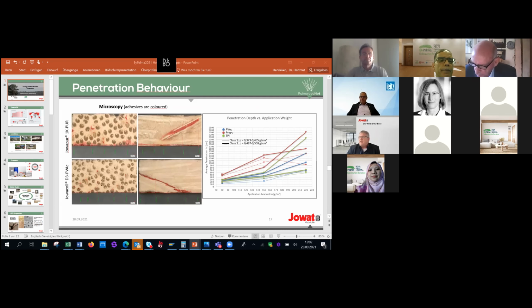So the penetration behavior. It seems clear that you have this soft parenchyma, that penetration is happening there. But actually, if you're looking into the pictures, you have quite some penetration in the parenchyma, but a lot happens also through the vascular bundles. So the adhesive is applied with pressure and is going through the bundles and is released inside the material somewhere. So we have a network of adhesive in the material. As you can see in a cross section here, a vascular bundle has been cut and it's filled with adhesive.